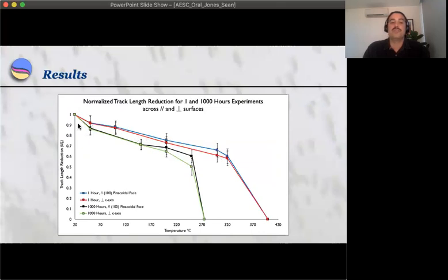As we can see, as annealing progresses, the mean track lengths are reduced and become anisotropic with crystallographic orientation, which means that tracks that have been implanted on surfaces oriented perpendicular to the c-axis always have a shorter mean track length than those implanted on the 100 face.